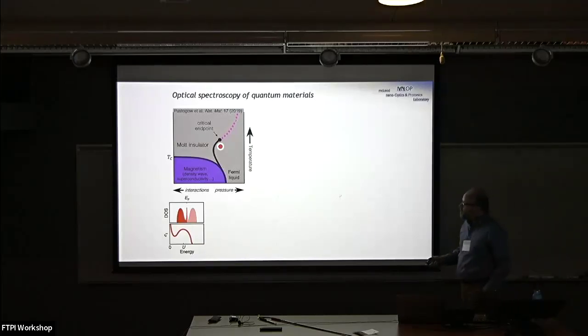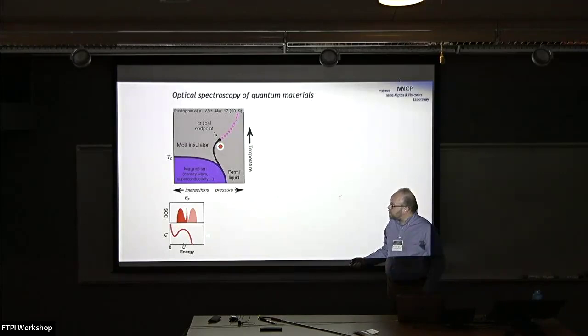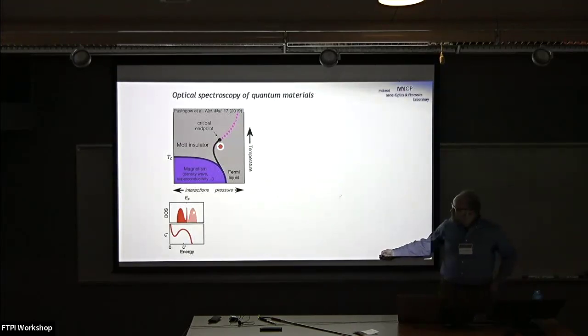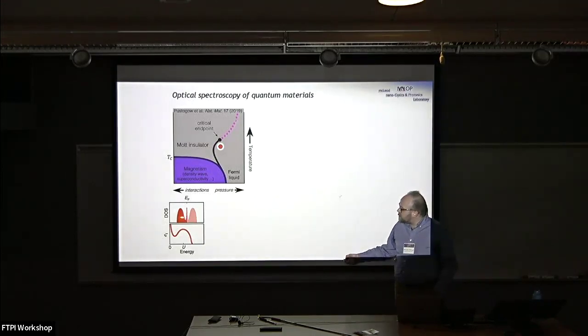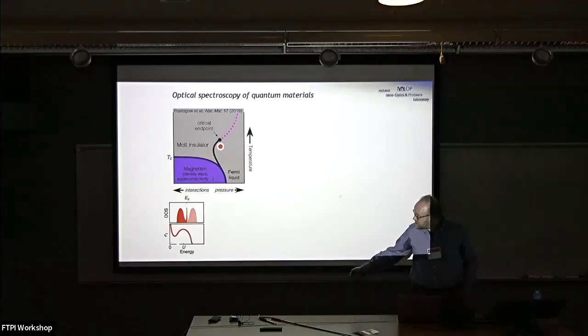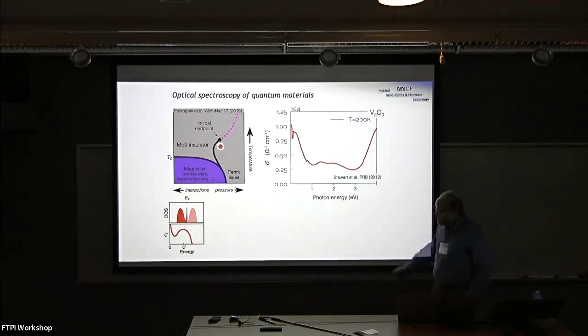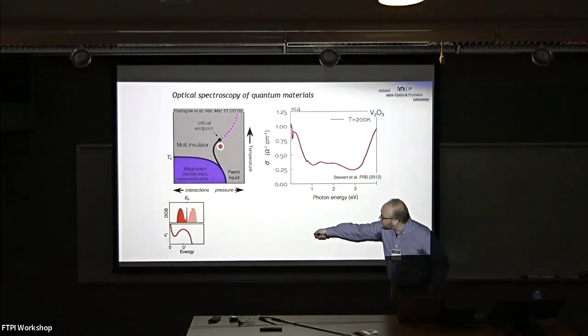And I'm just going to give you a flavor of what optics is actually measuring. Many of us have a concept of density of states. Okay, so if we're in the Fermi liquid, we have coherent quasi-particles at the Fermi level. There's some indications of interactions. So with our cartoon density of states comes a cartoon optical conductivity. Okay, so if one can do optical spectroscopy over some energy range, in principle, the information about density of states is encoded inside of the spectrum. And a characteristic in this case is the energy scale for interactions, the Hubbard U, which ought to show as a vestige of the joint density of states in transitions between upper and lower Hubbard bands here.